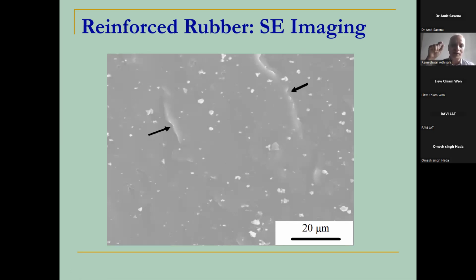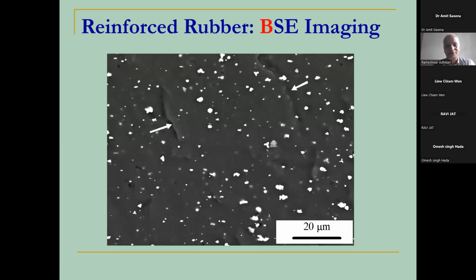If we image the same area with backscatter electrons, then we have this result. You can see that the darker areas are organic polymer, and these brighter areas are the areas in which more and more backscatter electrons are produced. Backscatter electrons are produced more by those areas which have higher atomic number, the inorganic substances.